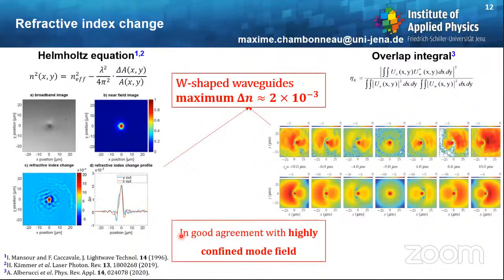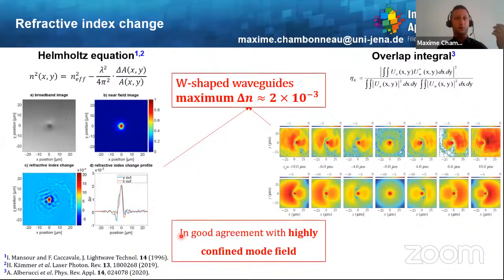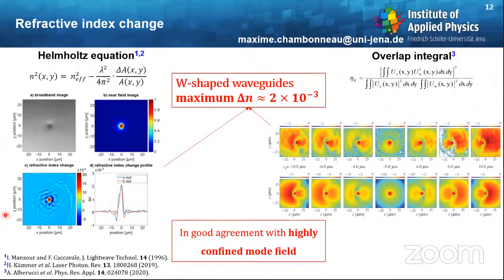Then we want to characterize the refractive index change of the material. Normally, if you can inscribe some waveguide, it means that you have a refractive index change, which should be positive most of the time for gradient index optics. And to characterize the refractive index change, we rely first on the Helmholtz equation shown here, which allows us to do some simulations of the light that we should theoretically detect.